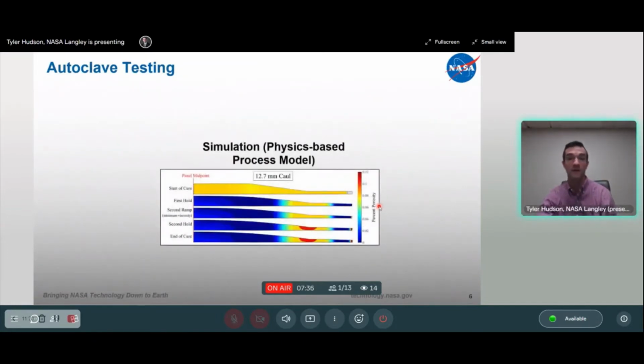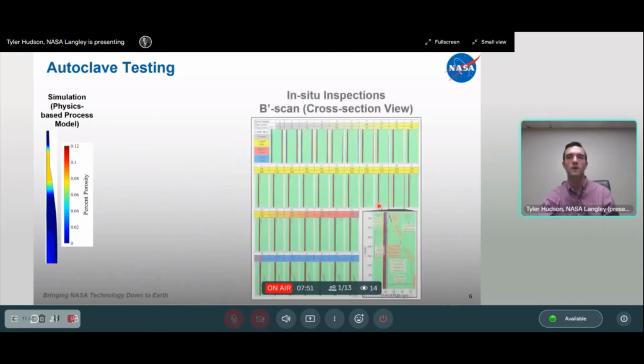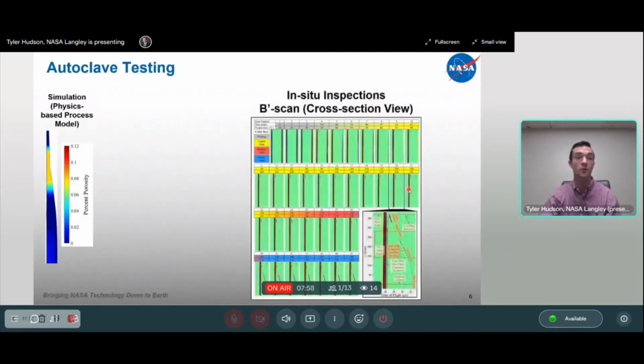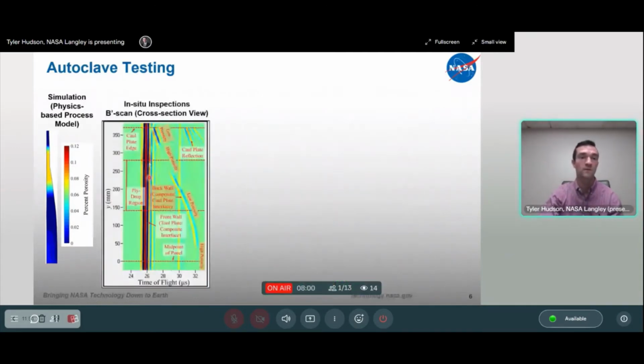Our autoclave testing, this puts it all together in just a really simple slide. So we have process models that can predict porosity throughout the entire cure cycle. If you pull out a single point, so this is in the B stage, when your resin is still liquid, we're doing inspections throughout the entire cure. If we pull out the particular scan that's at the same time in cure, this is one surface of the composite. This is the other surface of the composite.